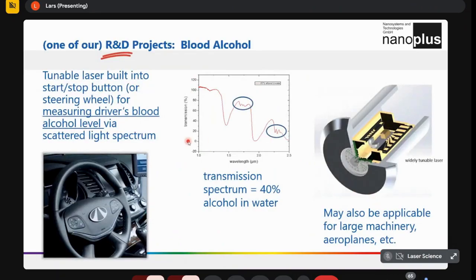That is used for very broad absorption profiles. So the gases, the small molecules I was talking about, for example, water vapor, they have a very small absorption profile, only something like, I don't know, 0.3 nanometers or something in that range. But if you look here, for example, at blood alcohol, they do have these features in blood, like these absorption profiles here. So if you could go with a laser over these absorption profiles from 1.5 micrometers all the way to 2.5 micrometers, then you can have this absorption profile and detect how much alcohol is in the blood of the driver.